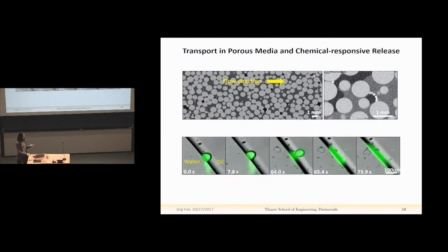And then we also characterize the release behavior of these capsules near an oil-water interface. We originally suspend some capsules in water, and we have an interface like this. We give an initial velocity to those capsules. So once these capsules reach the interface, they stay there. And because in this experiment we use a relatively high concentration of toluene, within seconds, this capsule started to release its cargo. And after about a minute, they suddenly burst and release all their cargo at the interface. So this, again, confirmed our hypothesis that these capsules are able to release their cargo near the oil-water interface.